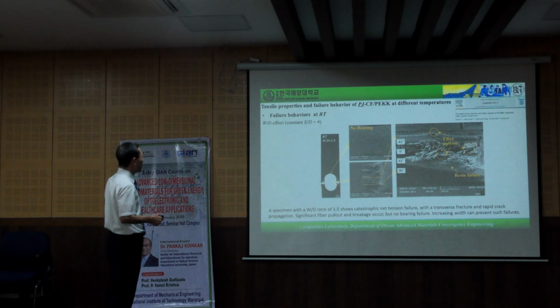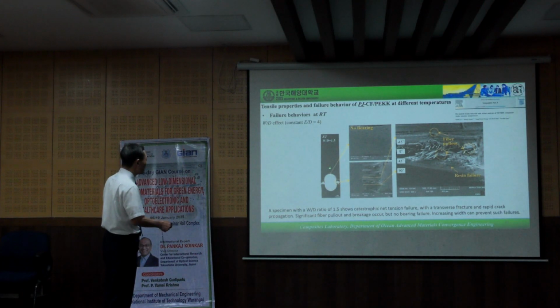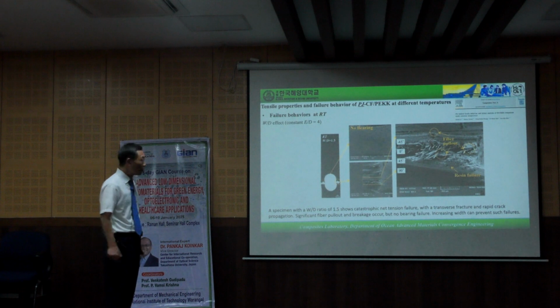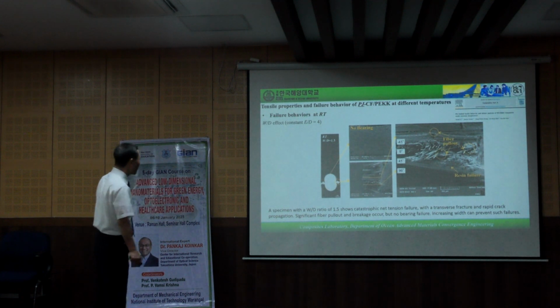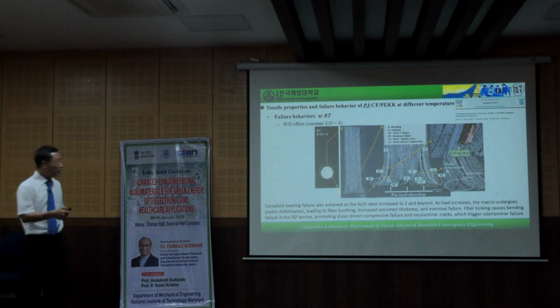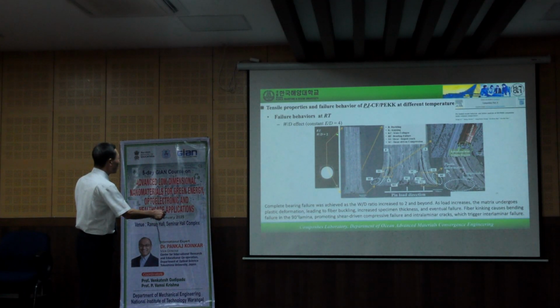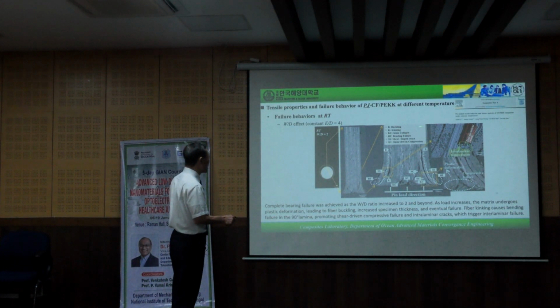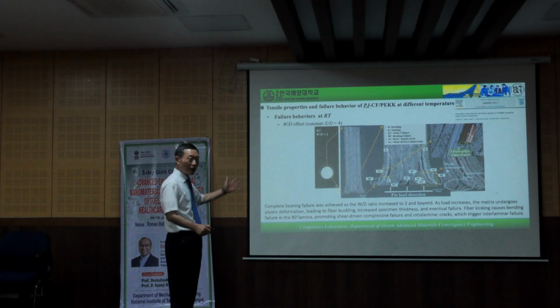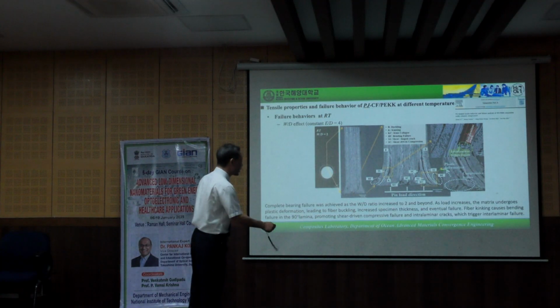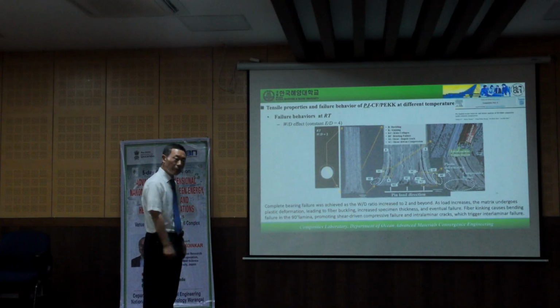Tensile property and failure behavior of pinned joint at different temperature, as failure behavior at the room temperature. W/D effect 1.5 net tension. The fracture morphology is right there. Just compare. In case of W/D equal 2, we observe here the fracture morphology is like this. Buckling and kinking and kink collapse and bending failure and shear shape crack and shear driven compressive. So we can observe the intralaminar crack and interlaminar crack. We can observe here. Very important result.